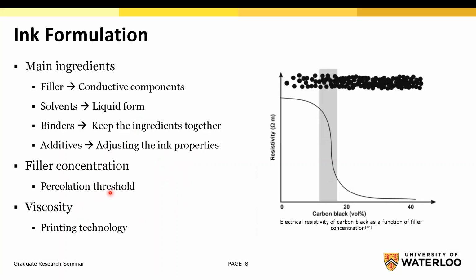The filler concentration of the ink depends on the percolation threshold. The percolation threshold is the concentration at which the matrix changes its characteristic drastically. For conductive inks, we can consider this characteristic change as going from non-conductive to conductive. Let's take a look at this plot. Here you can see the electrical resistivity as a function of filler concentration for carbon black. This also shows the carbon black particles at different concentrations. Initially, at low concentrations, the particles are not in contact and there is no conductive network between them. That's why resistivity is too high. When you keep increasing the filler concentration slowly, at some point there is a sudden change in resistivity from non-conductive to conductive.